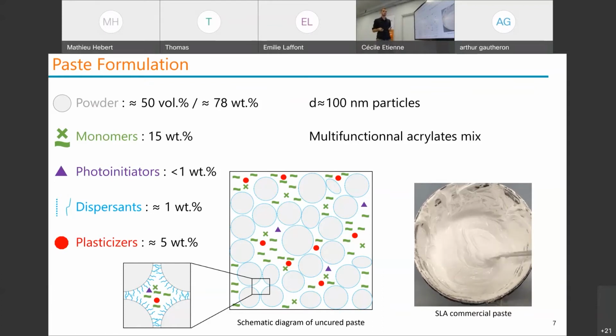I also need photoinitiators that are sensitive to the UV rays I send them, so they can initiate polymerization. Then I also have dispersants functionalized on my particles in order to repel the other particles and get a homogeneous paste. And I also have plasticizers that have different effects on the rheology of my paste, but they also permit to remove the constraints and avoid the formation of cracks even more during the debinding. So this is roughly what is in my paste.